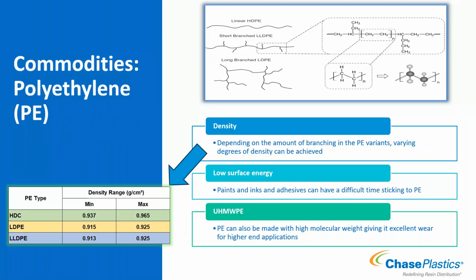So some additional information on it. Polyethylenes come in a variety of densities. So you might hear or use high density polyethylene, low density polyethylene, or linear low density polyethylene. That is 100% attributed to whether the material is branched or not. So for your high density polyethylenes, there is no branching that occurs, and that additional monomer is not growing basically off the side and branching out.